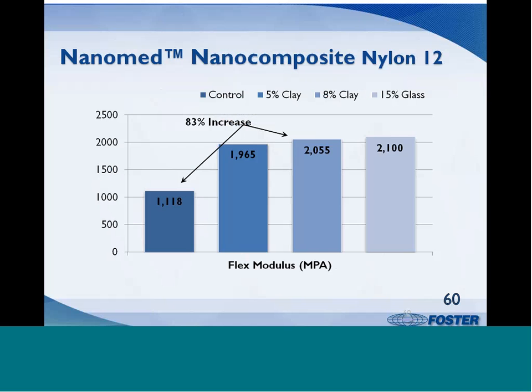Increasing amounts of nanoclay leads to increases in flexural modulus. Notably, 8% nanoclay approaches the flexural modulus of a fiberglass composite. Because of its size and brittleness, fiberglass is not necessarily an attractive reinforcement for small bore tubing, while nanoclay makes sense for such applications.